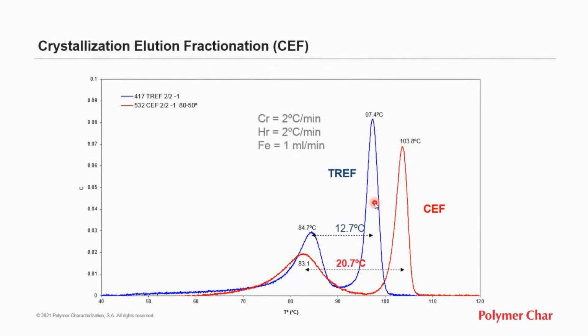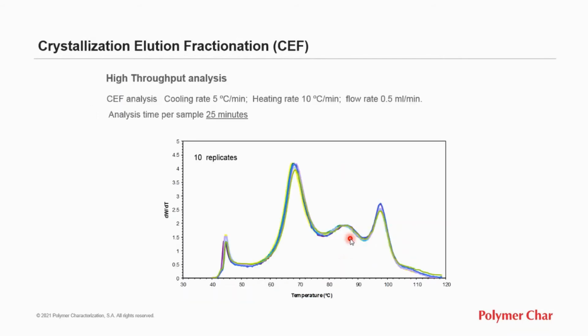As an application, we see here the analysis of two polyethylene products which are uniform but have slightly different densities. There's better resolution with CEF than with regular TREF when used in the same conditions, in the same analysis time. Those two polyethylene copolymers with similar densities, in CEF the separation was 20.7 degrees, which is larger than the separation obtained by TREF, only 12.7 degrees. So separation power of CEF is larger than TREF.